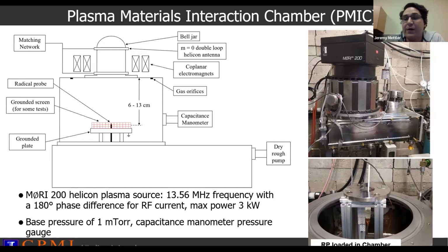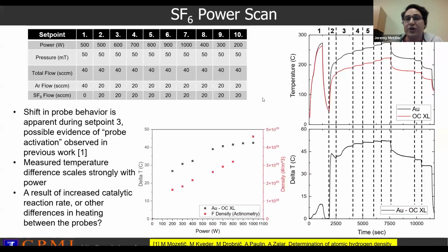And we sought to see if we could just at first find any material that might be suitable for acting as a catalyst for this fluorine recombination reaction. And I'll spare you all of the materials that we tested that didn't work and just jump straight to what we first saw had some promise, and that was actually gold, just like with hydrogen. And so here's an example of some of the results we obtained with the gold and OC XL probe next to each other in an SF6 plasma.